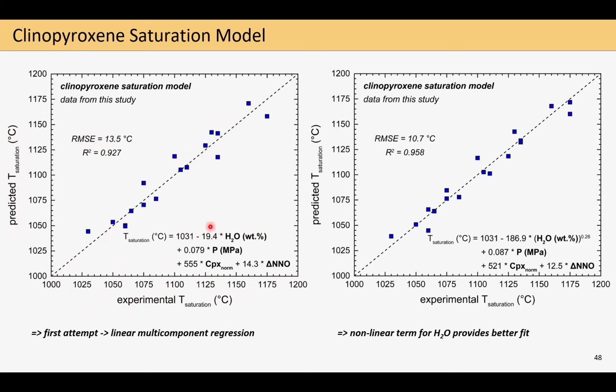However, now from literature we know that water contents tend to affect mineral stabilities non-linearly rather than linearly. And this is what I then accounted for in a new version of this model. So I added this exponential term here for water, and in fact the model slightly improved, so the errors became slightly lower and the R-square is now higher. So this seems already to work quite well.